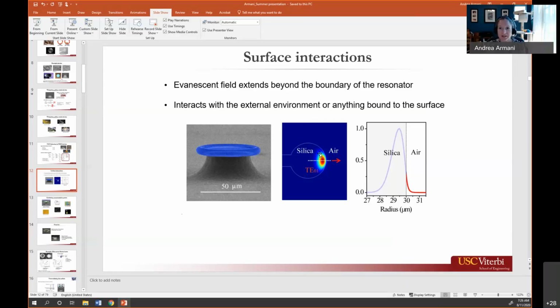That's a known threshold. It's common knowledge in the field, but we can calculate it. There are analytical calculations we can do. If you change the wavelength, then that value changes. But 25 to 30 microns is a safe bet if you want to maintain a Q over 10 to the 8th. I can give a paper on it. It was by Oraevsky and published in 1996 in Optics Letters. It's been cited like 10,000 times or something. Life goals.